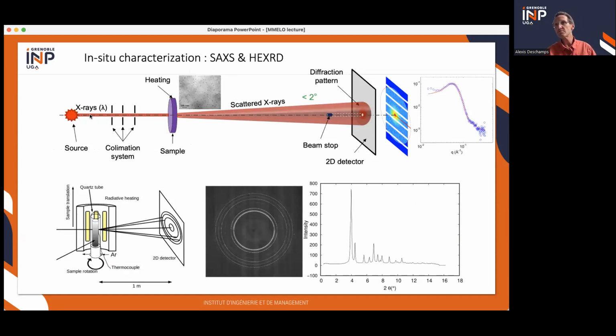This can be synchrotron or lab source. It needs to be quite parallel and thin. It goes through your sample, and the X-ray light is scattered by your precipitates, and you measure the scattering as a function of the angle, and it gives you an intensity profile that you can model and extract some data of the precipitate microstructure. And since you have a bulk sample, it's very easy to do in situ heat treatments.